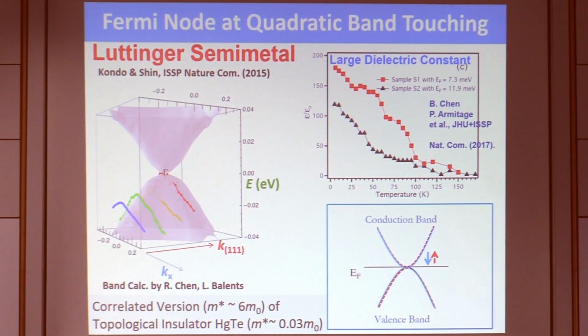And later, the Weyl metal prediction came, and some understanding of this material was also made. We now know that this is actually a class of Luttinger metal, namely a correlated version of topological insulator or mercury telluride. So this has a mass of 6 times, and it only has a Fermi point. There's no other Fermi surface at the Fermi energy, only a single point. So this is a gapless semiconductor. And this gaplessness shows up, for example, in a large dielectric constant. And this can be viewed as a mother state of the Weyl metal.